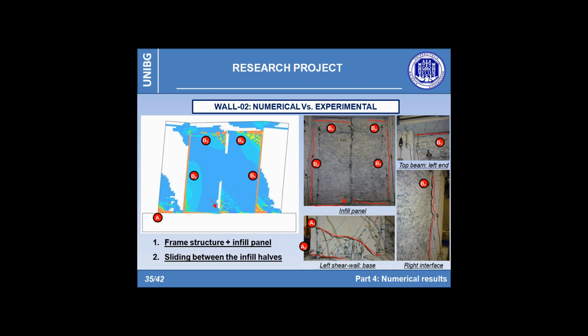Also in this case, the finite element model has proven able to catch the main mechanism observed during the test, especially correctly assessing the contribution in terms of bearing capacity offered by the infill. The choice to model the initial shrinkage crack as a plane of weakness proved efficient in reproducing the interaction between infill and structure.